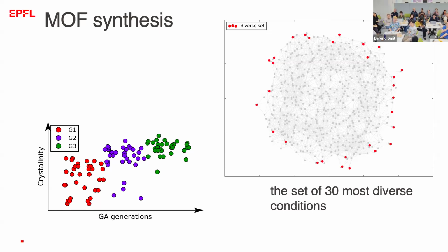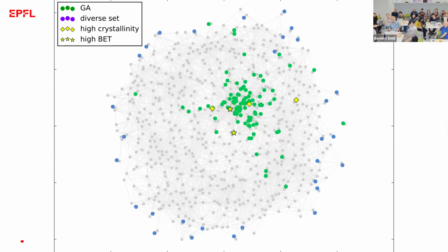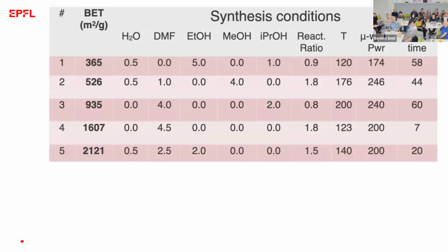Okay, then you had those samples, and then we organized a bingo. And the bingo was the following. Depending on the happiness, you could either get 0 balls with the experimental conditions, or say 10 of those balls. You roll it and you draw parents. And then you do these typical genetic operations. And what you then see is it's improving, in this case the happiness or the crystallinity. And if you see what's happening, you start to sample the interior, and on the yellow points, we were very happy, and we did the BET surface.